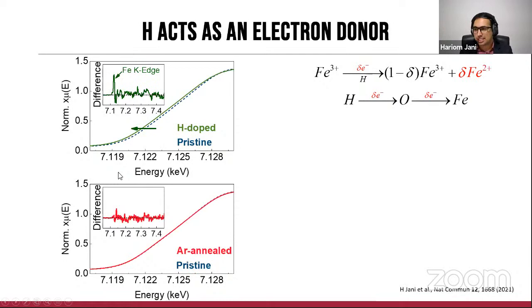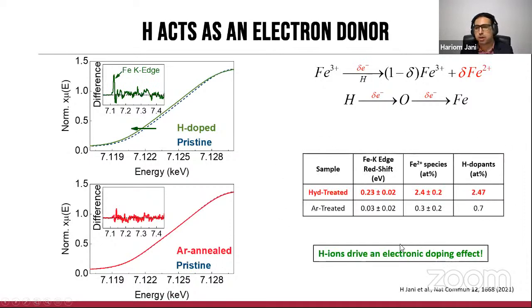which actually then suggests that hydrogen is resulting in some form of electronic doping. And this occurs because the hydrogen tends to form bonds with oxygen preferentially, and this therefore weakens the oxygen iron bond, therefore shifting some kind of electrons back to the cations. We can do this quite quantitatively as well, where we compare the shifts with respect to the hydrogen dopant concentration, and we actually find that there is some reasonable correspondence.